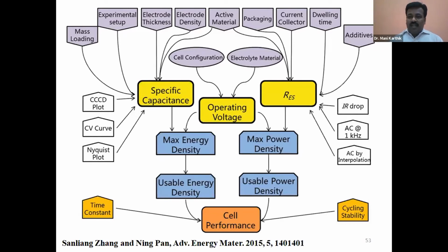So if we increase, for example, at Maxwell's and the commercial level, we need to coat more than 10 mg per square centimeter. But 10 mg per square centimeter of active carbon is a challenging task, because if we coat more or coat less, you have a problem with the measuring or whatever. So this is the commercial standard.